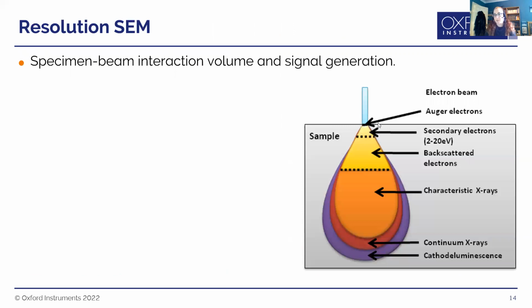Now, one of the key things about specimen beam interactions is the volume. As your beam hits your sample, you have a large volume where the electrons from the main beam interact with your specimen, and you get emittance of all the different signals from all those areas that the beam interacts with, but only certain layers can leave the surface of the sample. So here, where we've got the main beam electron, we've got this area just below the surface where secondary electrons can be emitted and detected. They will be emitted throughout this entire volume, but we can only detect those that leave the sample from this region. Slightly deeper on, we get a signal of backscattered electrons, and then we get the X-ray signals generated much deeper within the sample. And this is quite important because it affects the resolution of the data you get.